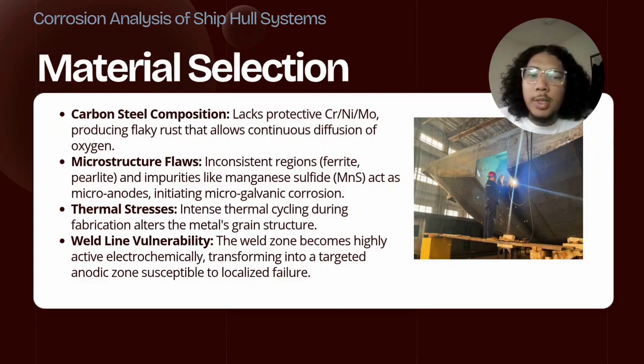For cost and malleability, hulls are made of carbon steel. However, unlike stainless steel, carbon steel lacks chromium and nickel, meaning the rust it forms is flaky and porous, allowing oxygen and water to pass right through. Furthermore, carbon steel has a non-uniform microstructure. Impurities like manganese sulfide act as tiny microanodes, initiating microscopic galvanic cells across the entire plate. Finally, the welding process itself introduces intense thermal cycling, altering the grain structure and leaving the weld line highly susceptible to localized attack.